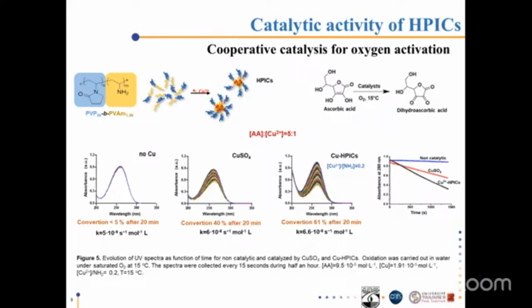As controls, the oxidation of ascorbic acid without catalyst and in the presence of copper sulfate were also examined. The oxidation of ascorbic acid was followed by the decrease in its absorption at 260 nanometers. As we can see from the picture, in the absence of copper catalyst, the conversion of ascorbic acid is below 5% after 20 minutes.